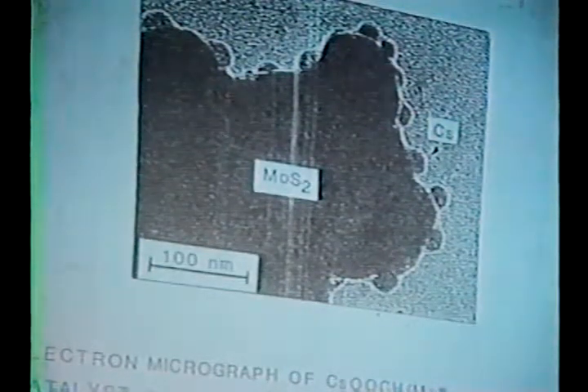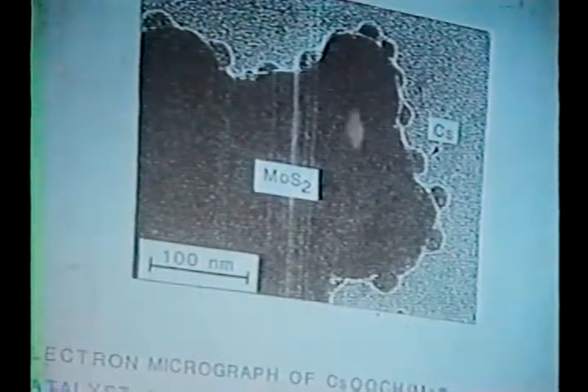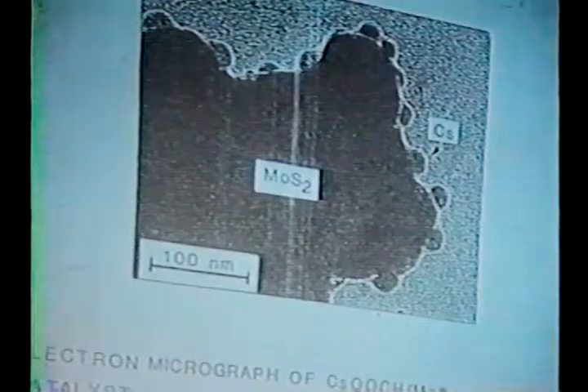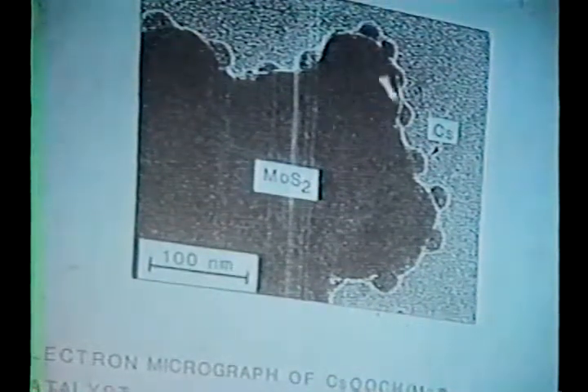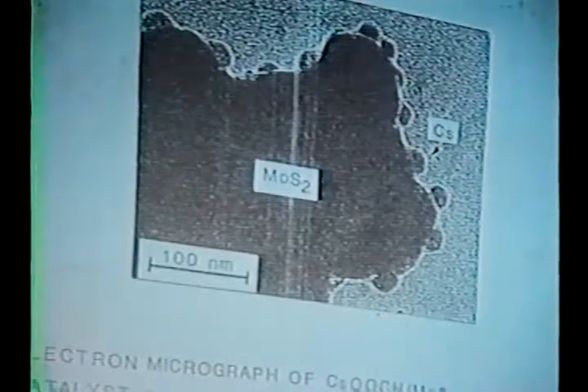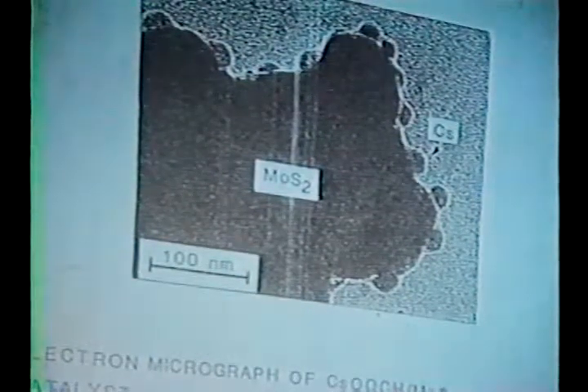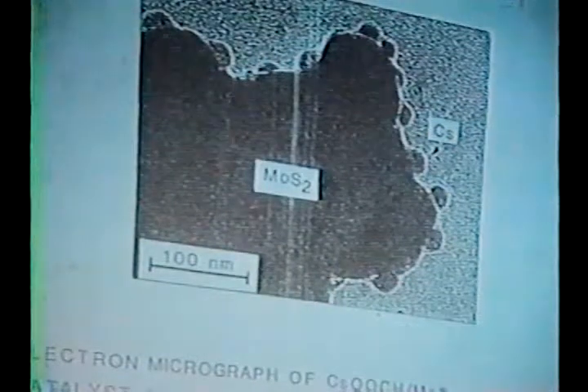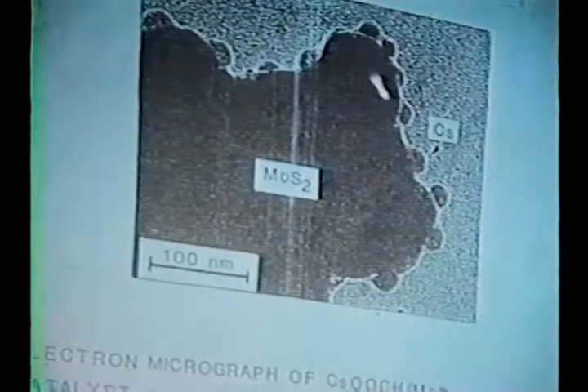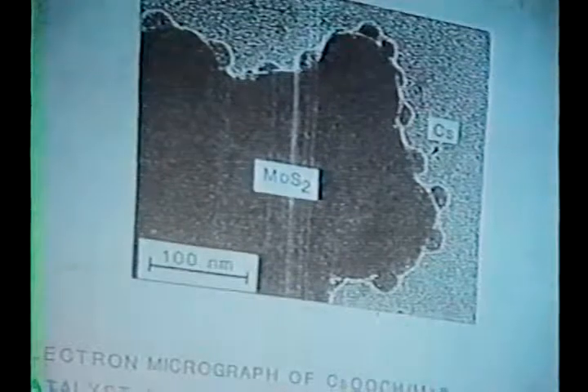When I talk to my colleagues, colloid chemists, they say they can't explain this by dipole repulsion interaction, but there is a possibility that the cesium will hold a charge, that the cesium, which is a neutral compound to begin with, will just become charged, and a small amount of positive or negative charge will be sufficient to maintain this dispersion. Now, just an idea which we pursued a little bit by looking at a spectroscopy which somewhat allows us to say something about those charges.